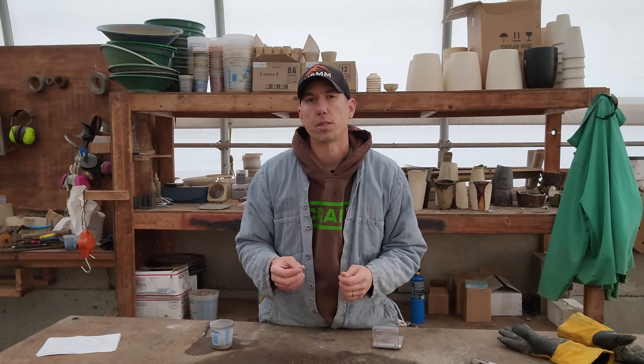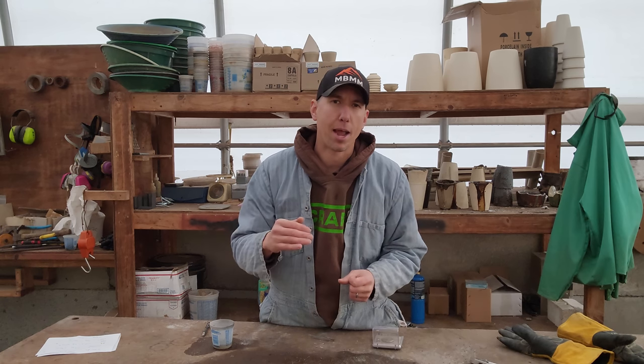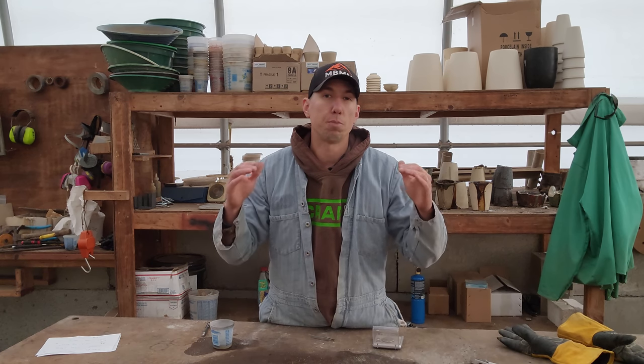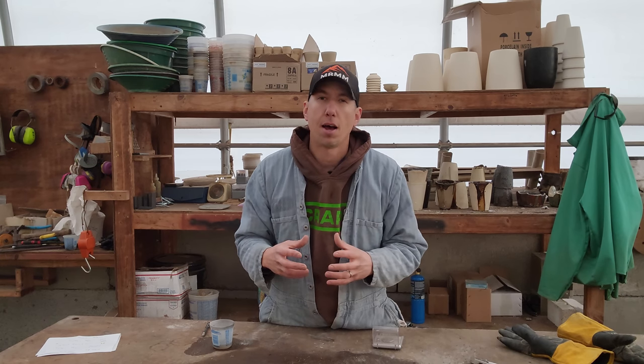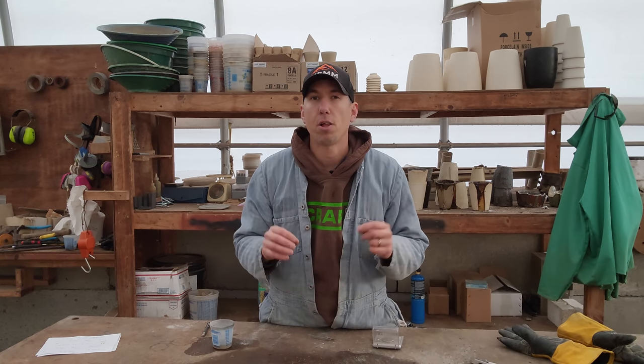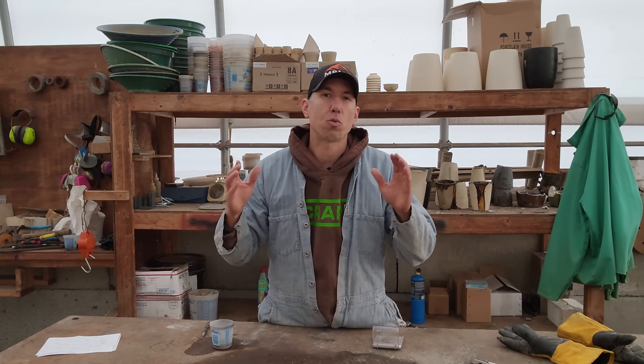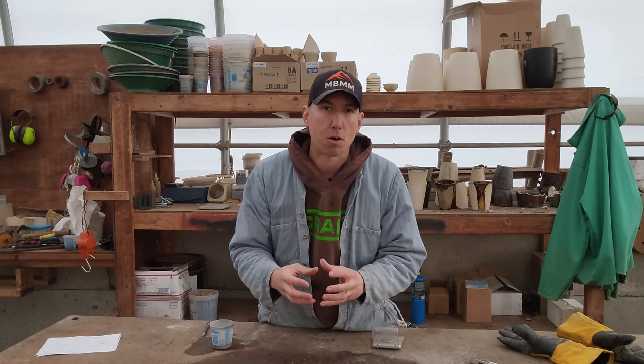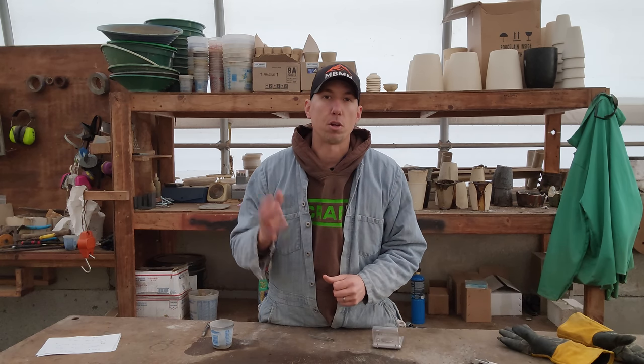Also, the thing that was kind of hamstringing me there was I didn't have enough borax in the melt. My crucible was too full by the time that I had it all molten, and it was just too thick. So even if you did have a significant amount of collector metal, there's a chance that some of those collector metal pieces could have been suspended in the slag anyway. So that is why I didn't get a bead or a collection of precious metals down at the bottom when I poured. So I learned my lesson there.